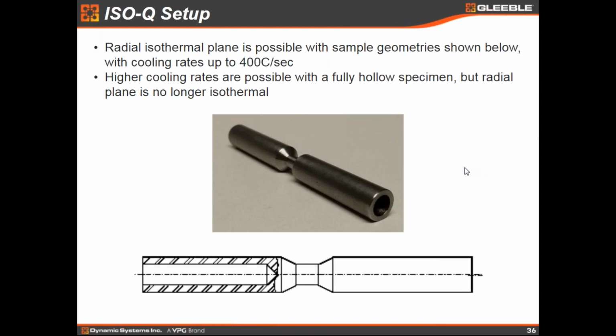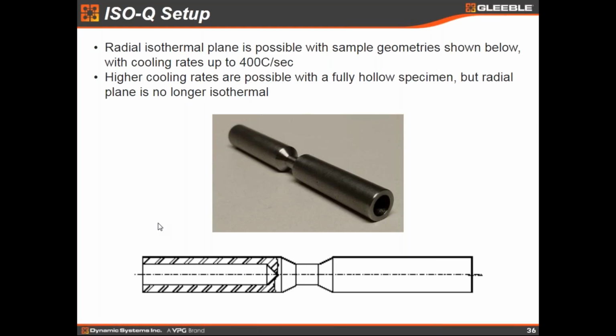So Brian already talked about the general geometry. Again, shown here, there's a hole bored through most of the way, not quite all the way into the sample. That's our typical geometry. That maintains a pretty good radial isothermal plane, and cooling rates up to 400 C per second are reasonable to expect in this. We can go higher than that. We have designs for samples that bore the hole all the way through the sample, with which you can get significantly higher cooling rates, 1000 C per second and beyond.